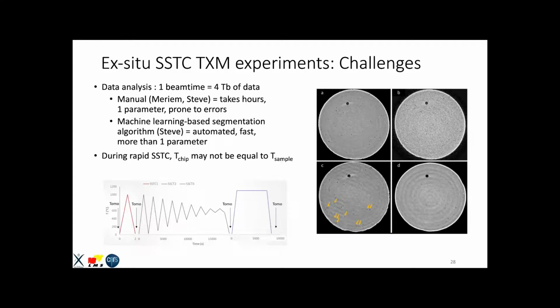Okay, the other challenge is during rapid solid state thermal cycling, the temperature of the chip that we use to heat the sample may not be the same as the temperature of the sample. And so there is an uncertainty in the amount of the heat transferred to the sample. And this was a challenge because we needed to find a way to solve this problem, and we did actually.